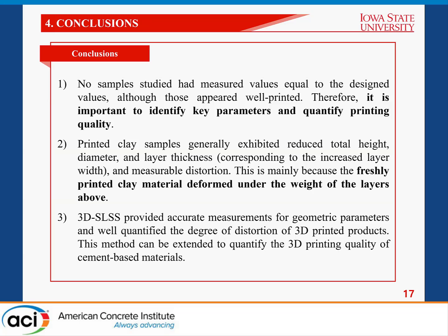This is mainly because the freshly printed clay material deformed under the weight of the layers above. And the 3D SLSS provided accurate measurements for geometric parameters and well quantified the degree of distortion of 3D printed products. This method can be extended to quantify the 3D printing quality of cement-based materials.